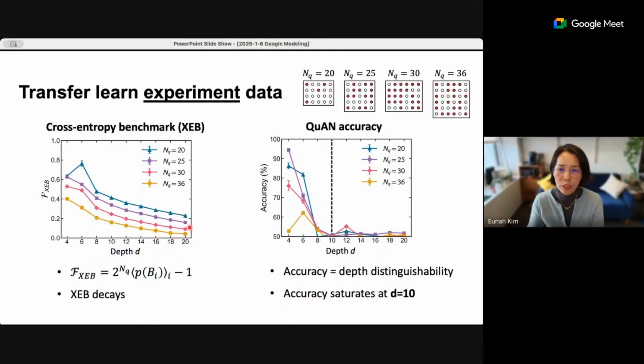So this is not showing any change in the depth, but when we use QuAN that was trained on simulated data, even with the noisy experimental data, it was able to find features in the data that really resemble the change in the complexity in the perfect data. So the fact that we were able to see a similar kind of change in distinction between shallow states and deep states, and recognize these lower depths as shallow states, was really encouraging as a way of giving us the insight that this architecture was able to learn the complexity of this state in a way that is meaningful and transferable to real world data.